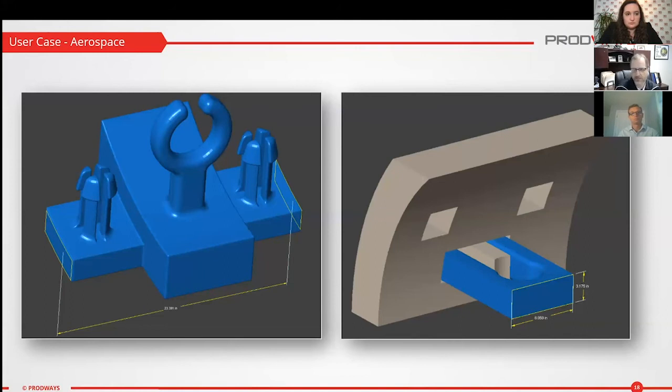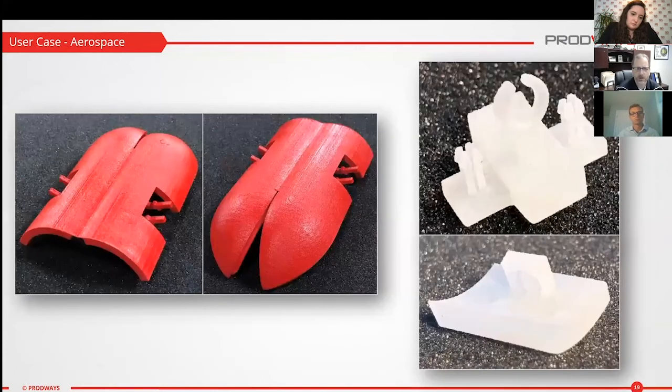So those were CAD pictures. As we move to the next slide, these are actual physical parts that were built. There's the same parts we saw in CAD. The left side, it's now been painted red, minimal benching, so you can actually see the layer lines, which was acceptable to this customer. But those are the actual parts that were built. On the right side, there's that same barbed features on the left and right with the clip in the middle. And this is, again, polypropylene, which runs at about a 70 micron particle size.